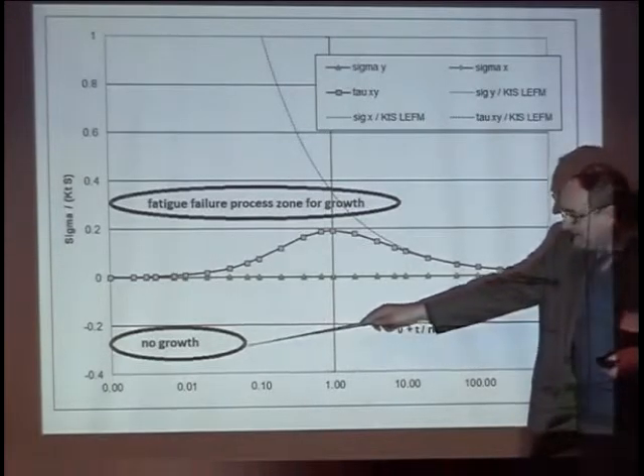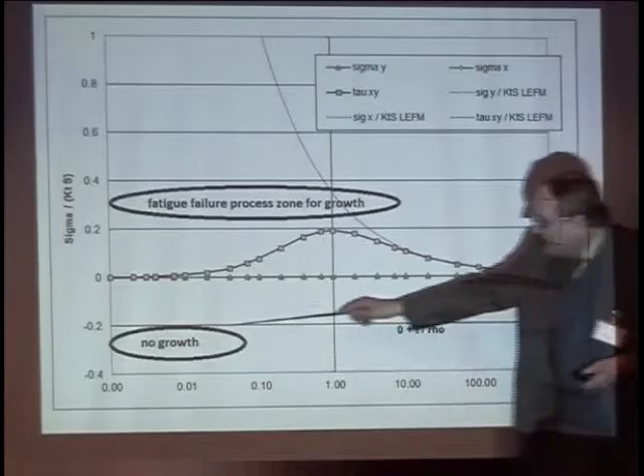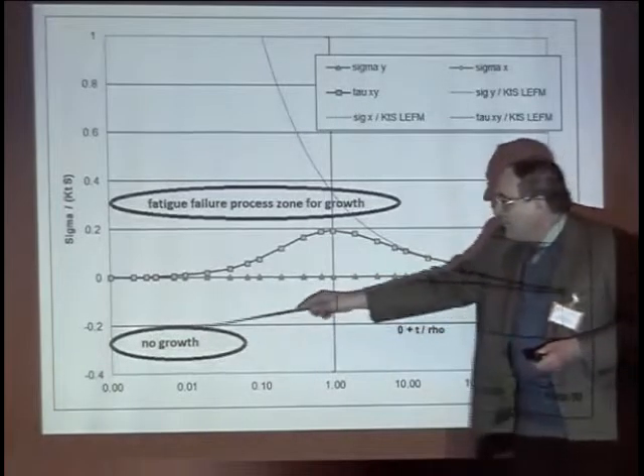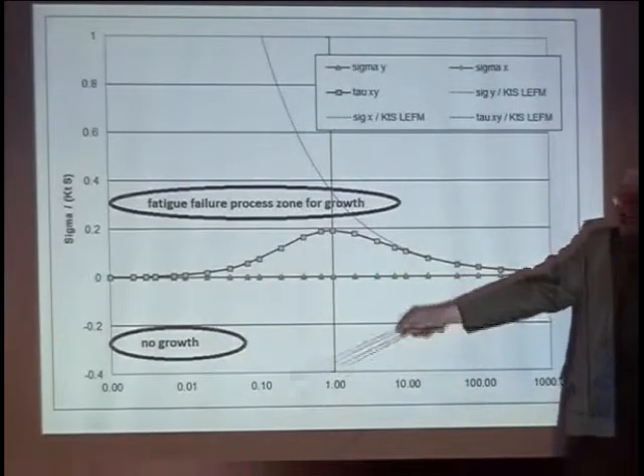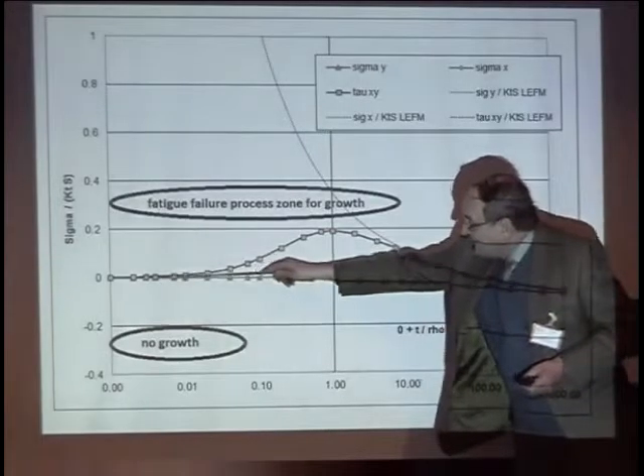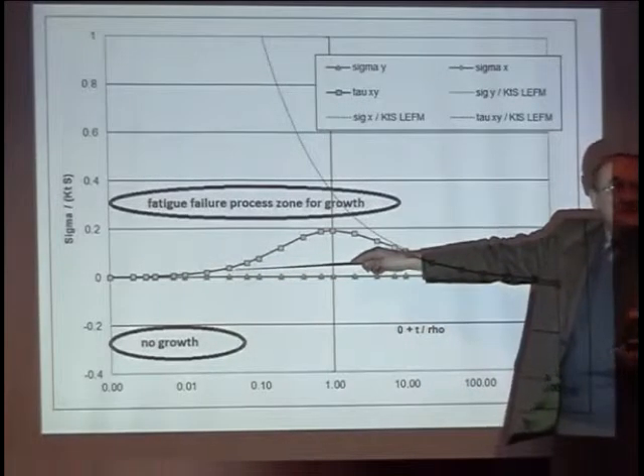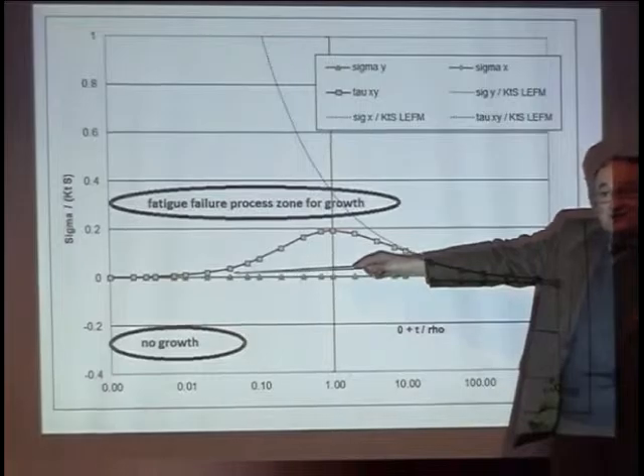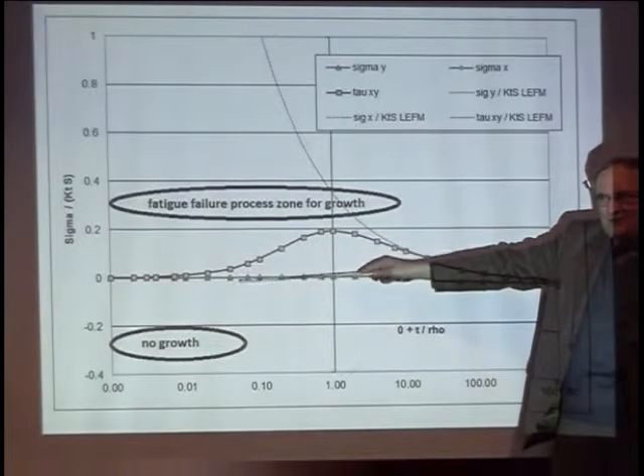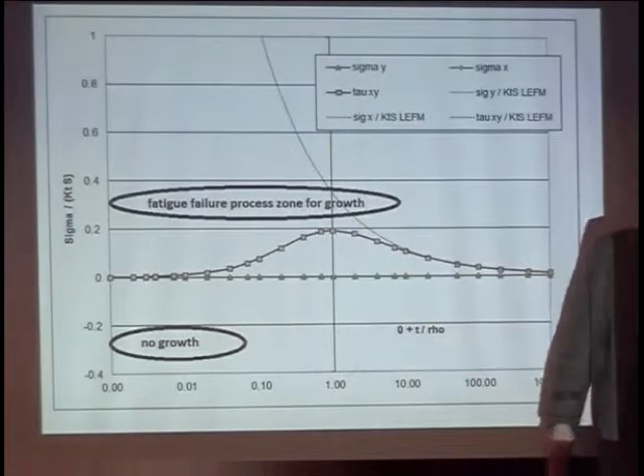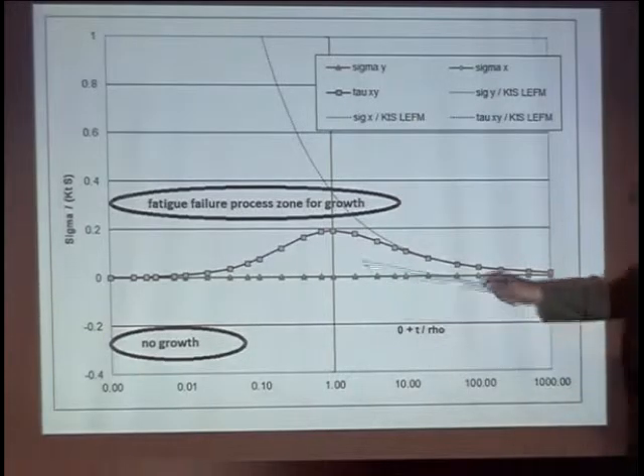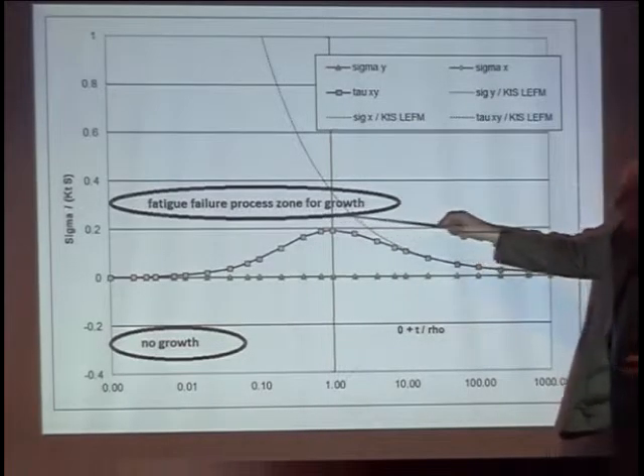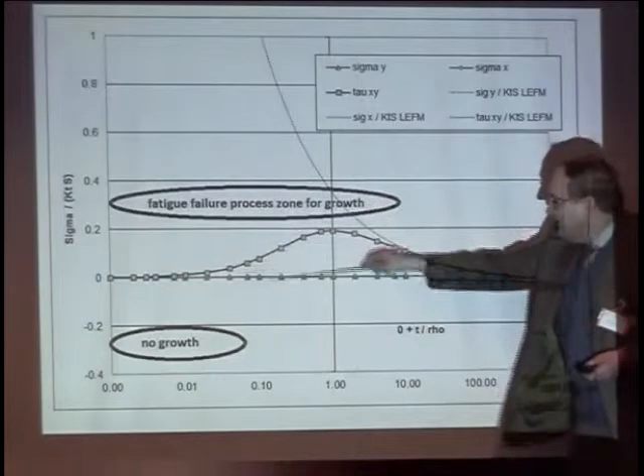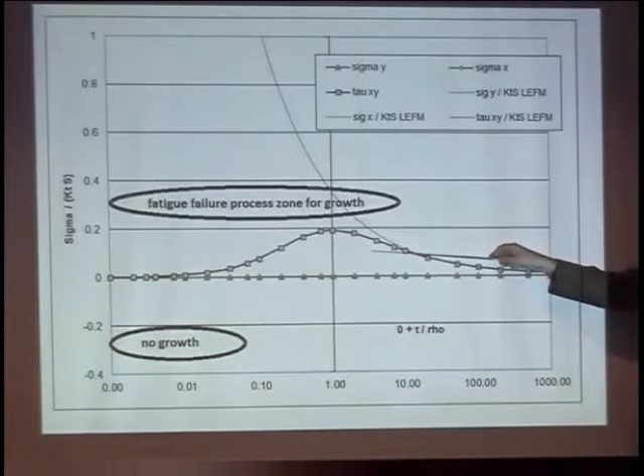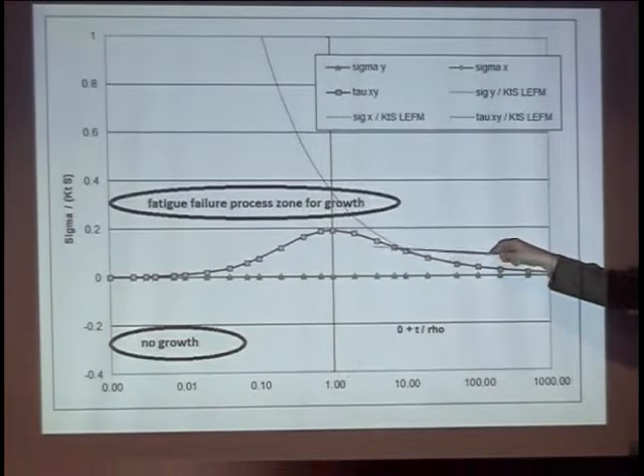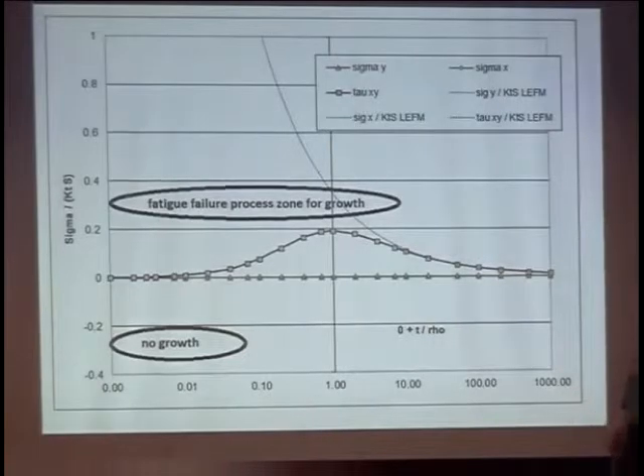This is the Sheffield case here. The process zone from the crack tip was presumably finite, but it wasn't big enough to get into a region where there's any significant stress. If you've got no stress intensity, or no intensity of stress, let's say, then nothing happens. And when I go to the Otsuka test, in her case, the process zone is often bigger, and therefore it includes these big stresses here, and therefore there's a good intensity of stress in the crack growth and shear.